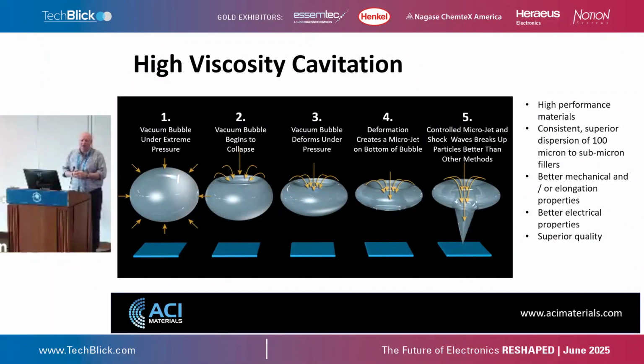And the way cavitation works, if you've ever seen a propeller on a speedboat, if you spin it too fast, you create vacuum bubbles, which then implode, and they start to erode the impeller. This is the same sort of theory behind high viscosity cavitation: we are forcing materials through and creating these small vacuum bubbles which create these very high energy jets that break agglomerates apart. And it really gives very high performance coatings, especially with metallic silver flakes and other things, as well as carbon nanotubes, graphene, and certain pigments and other particles that are difficult to disperse and stabilize.